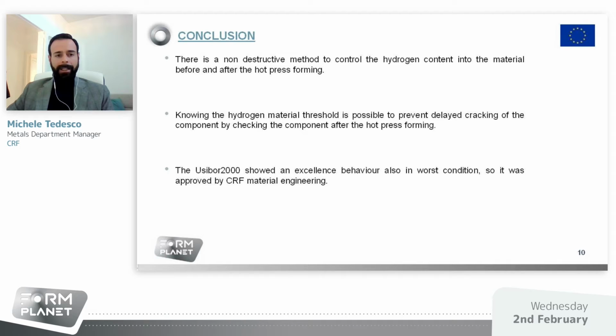In conclusion, we can say that there is a non-destructive method to control the hydrogen content in the material before and after the hot press forming. Knowing the hydrogen material threshold, it is possible to prevent delayed cracking of the component by checking the component after the hot press forming. So this gives us the opportunity to have claims after the component production.